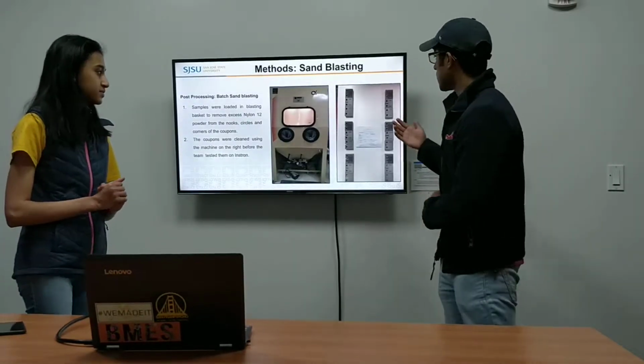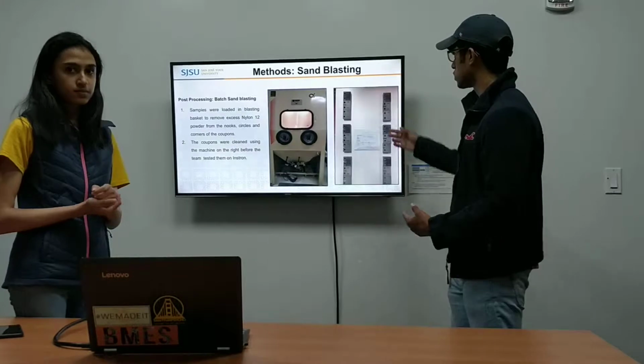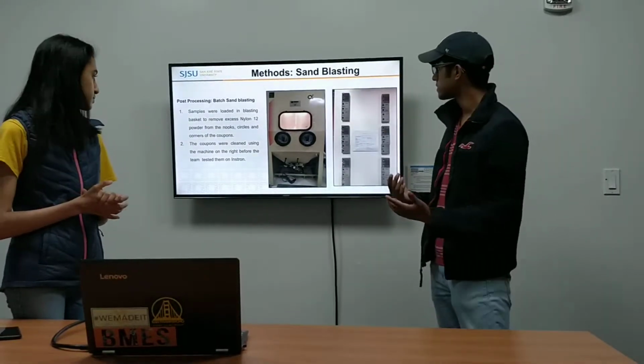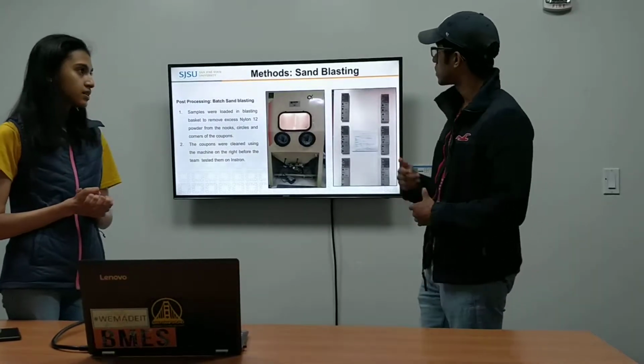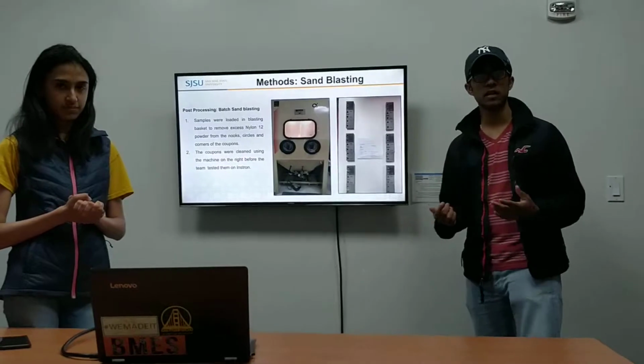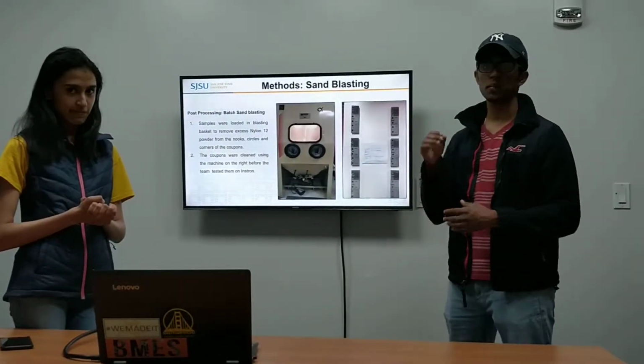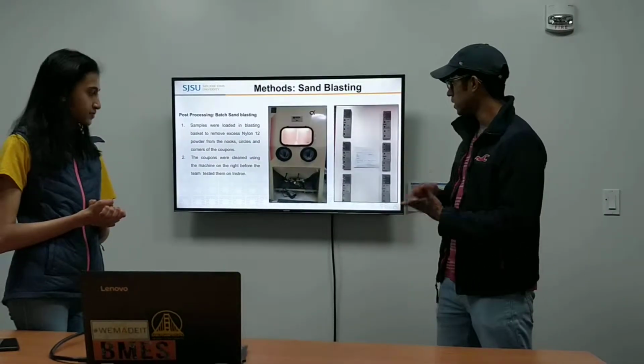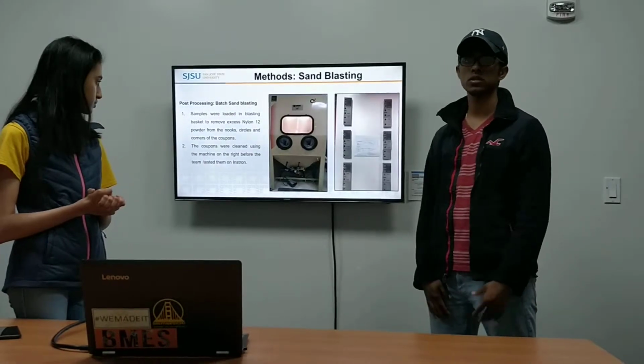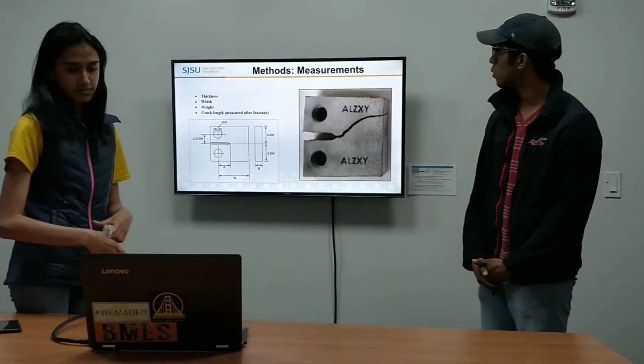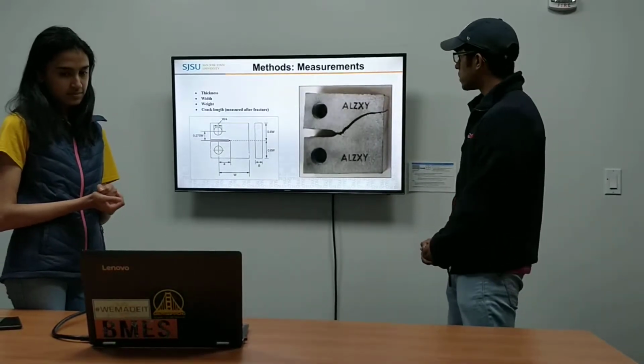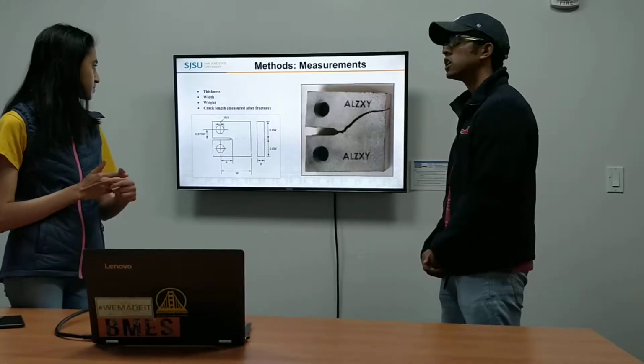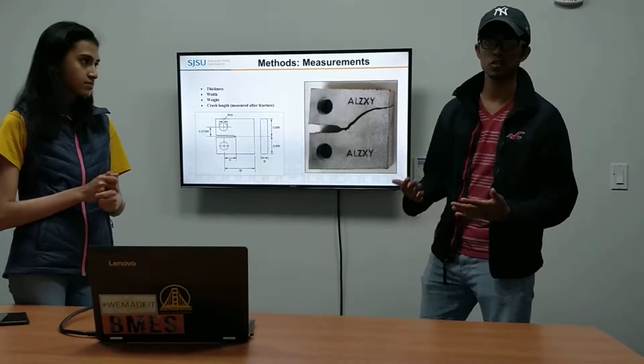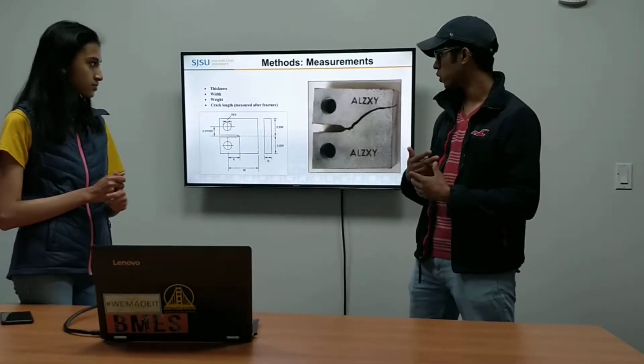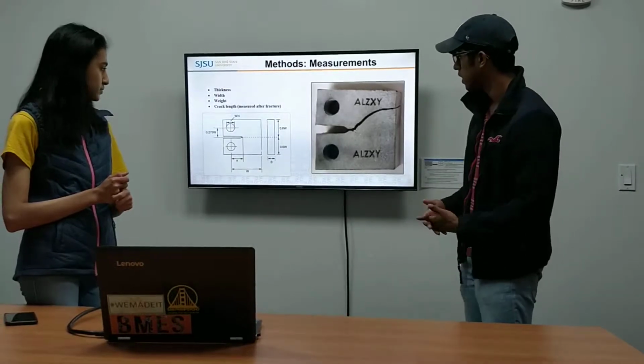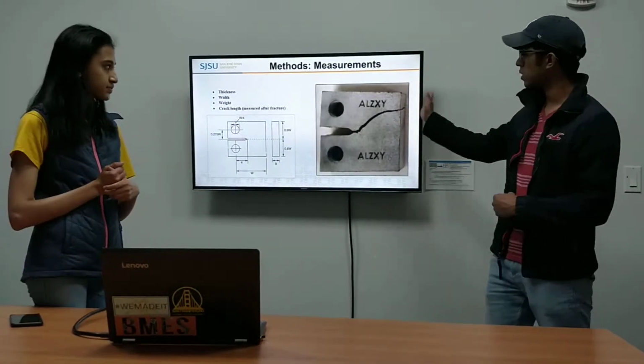Another thing that I left out was that all our samples are labeled so that we can identify them. There are 2 labels on both top and bottom end so that we can identify the samples once they're fractured and also before. Once we get our samples from the Jabil manufacturing team, we'll be sandblasting them. This is so that the nylon 12 powder that is inherently on top of the specimens can be removed, so our specimens are clean before we start any experimentation. Once the specimens are cleaned using sandblast, we will measure the thickness, width, and weight of each specimen, just to keep track of the dimensional consistency of all our specimens before we induce crack propagation. And this is a schematic of how the crack propagated in one of our samples, which we'll talk about more.